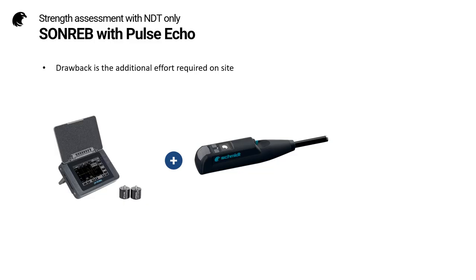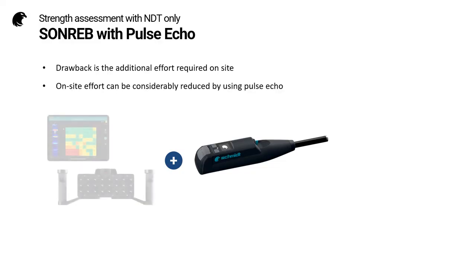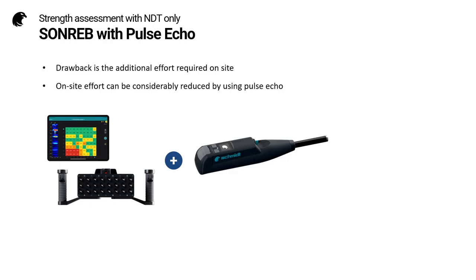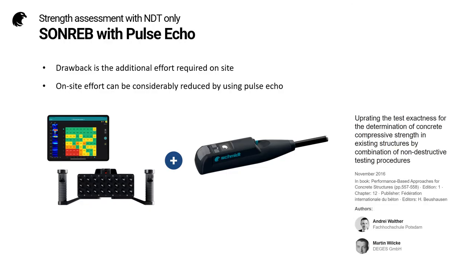The main drawback to the SONREB method is the additional effort required on site, but this effort can be significantly reduced if we use pulse echo to measure the pulse velocity, and this is a technique which I first saw successfully demonstrated at an FIB conference back in 2016, and of course since that time the pulse echo technique has become standardized.